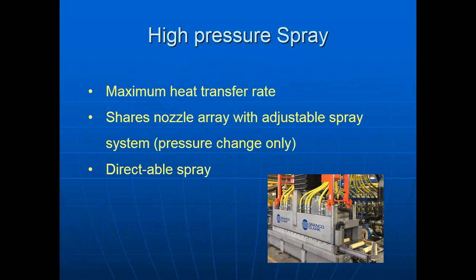In our case, we share the same nozzle array as our standard spray. So we can give you a normal water spray and a high pressure spray with a single set of nozzles just by changing the pressure. But by knocking down the steam barrier or allowing the steam barrier to reform, you have some very significantly different performance characteristics. So it really is like having two completely different modes or medias, even though it's the same nozzle.